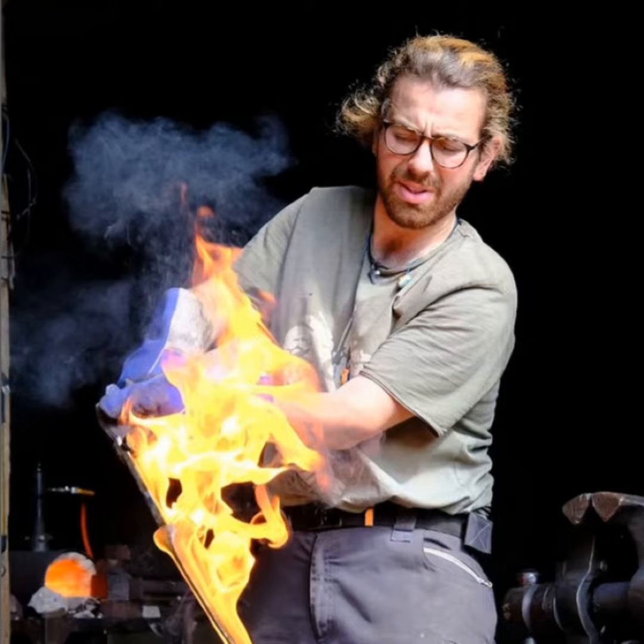Well, actually, I do have different grits from 1400 grit till, man, I don't know. I have a Honyama stone. It has like 15,000 grit, but it doesn't really work with it's not. Those stones are natural, so they don't really match one grit perfectly every time. So there's some finer abrasive in it, and there's something that's more porous, and then there's the slurry, and you have to work with the slurry that is created by abrading the stone in the water, and with that you get your contrast in your cladding material versus the